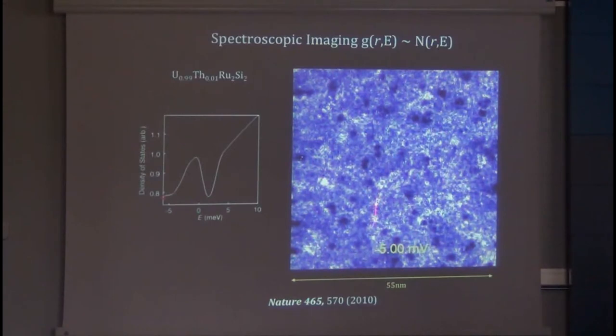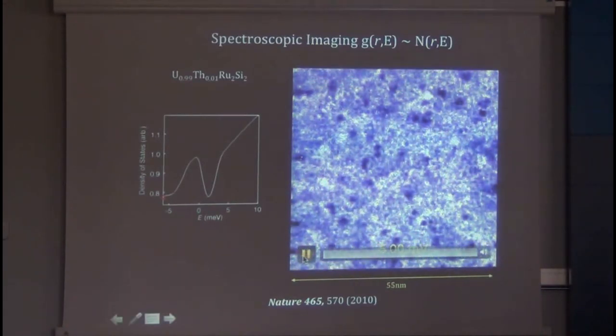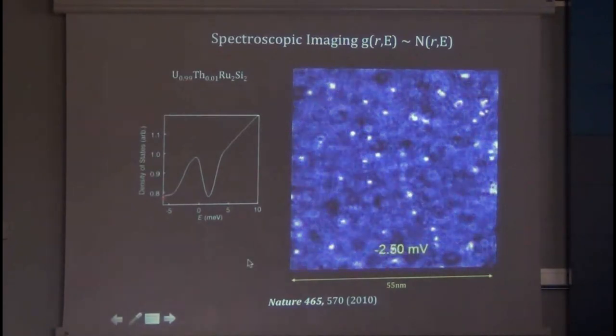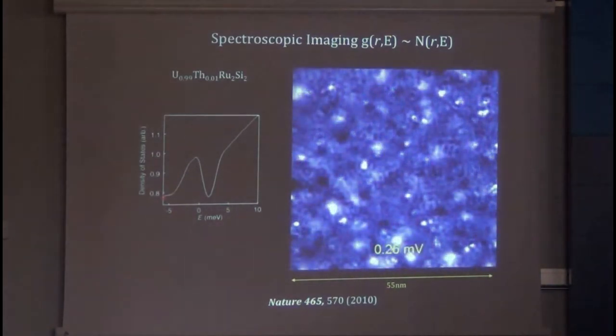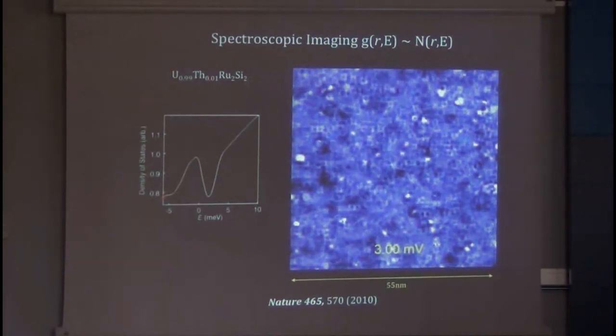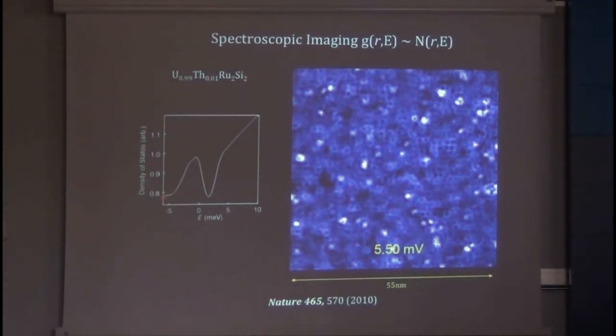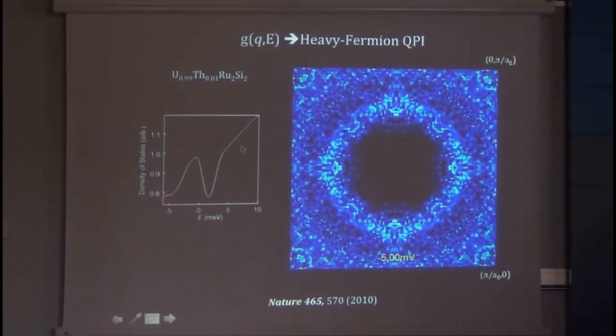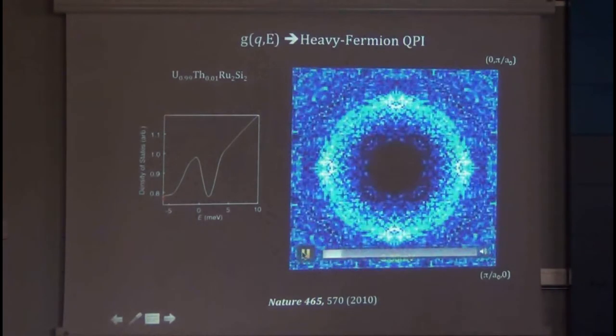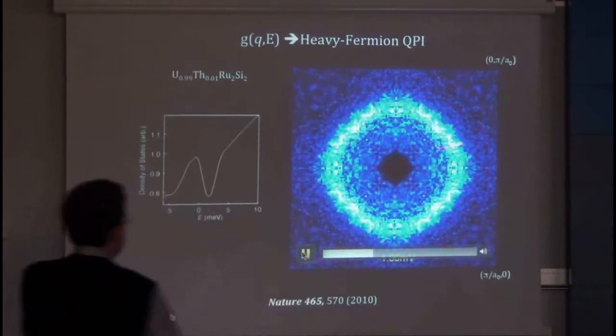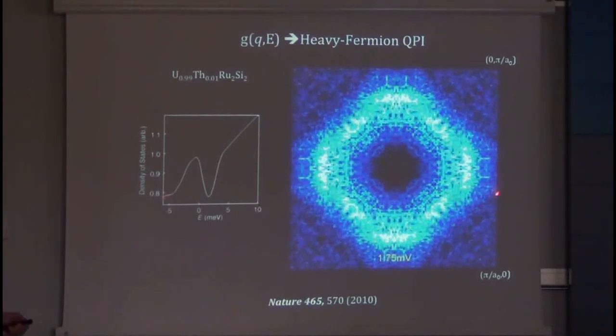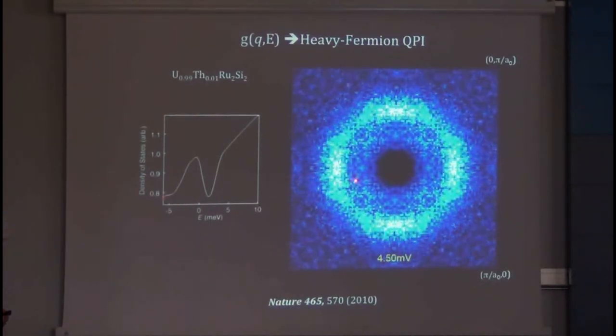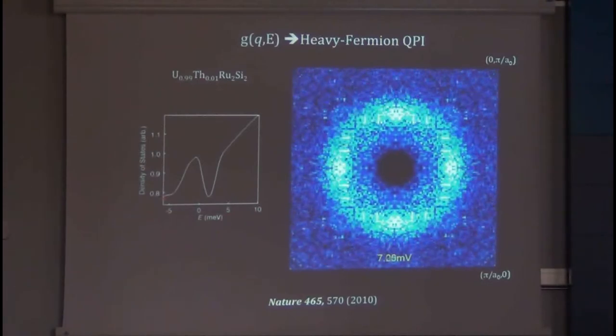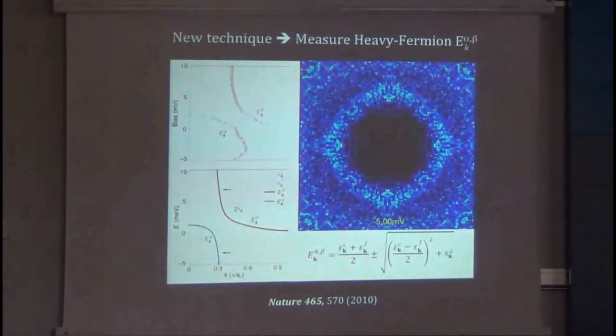And now you'll see the energy range of this image is only a few millivolts wide. But there's a great deal of activity in the wave functions. That's the heavy band, and now it's gone. And if I show you the Fourier transform, I can't tell you how happy we were to see this movie. It starts out at a large radius, it moves to a small radius, then it jumps back to a large radius, and then it moves to a small radius again. That's exactly what we were expecting to see.